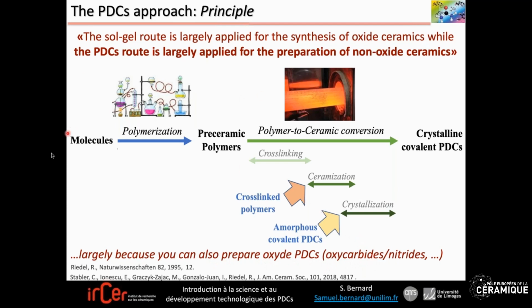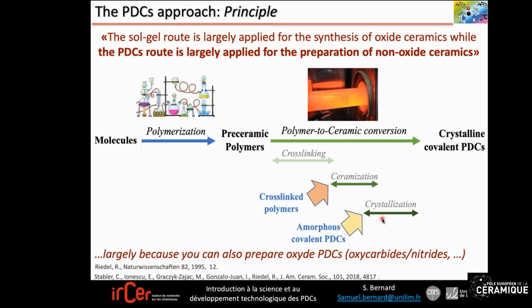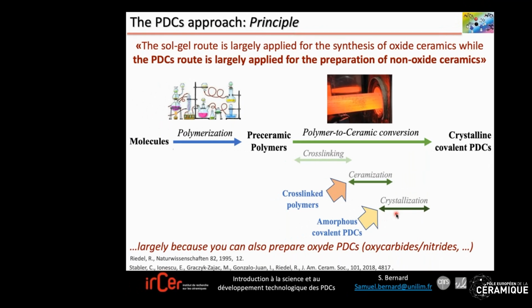So a flow diagram of the single steps involved in the production of PDCs is presented here. The processing of PDCs via the pre-ceramic polymers usually occurs in an atmosphere free of air and moisture, because you want to prepare non-oxide ceramics, and involves their synthesis from molecules, commercially available or homemade, their cross-linking to increase their molecular weight, their pyrolysis to transform the cross-linked polymer into an amorphous covalent PDC, and an optional heat treatment at the end of the process to form crystalline ceramic.